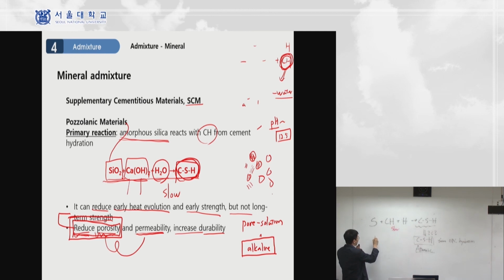And why can we reduce porosity? Because we can increase this calcium silicate hydrate, right? First, in the final stage, we can expect there is more calcium silicate hydrate, right? Calcium silicate hydrate formation needs volume, needs empty space. So if there's more generation of calcium silicate hydrate, then we can expect it has less porosity.